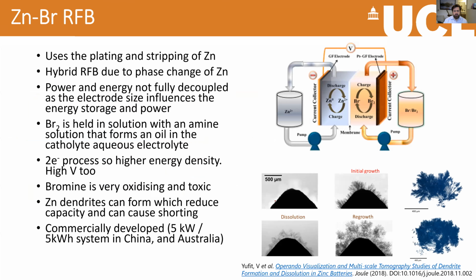Another well-developed chemistry is the zinc-bromine flow battery, and this actually uses the effect of plating and stripping metallic zinc. So you're depositing metallic zinc on the surface of your electrode, and then you're dissolving it when you're doing the opposite reaction. Because of that, it's known as a hybrid redox flow battery, but also crucially, the power and the energy are not fully decoupled in this system, because the amount of zinc that you can plate onto your electrode is dependent on the size of your electrode, the surface area that you have. And there's some other issues with this in terms of the toxicity of bromine and also the miscibility of bromine in aqueous electrolytes. And so you need to add other things into the electrolyte to help that to work. Nonetheless, there are commercially developed systems here.